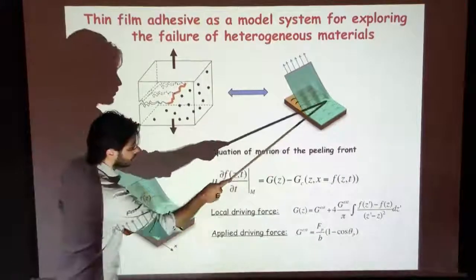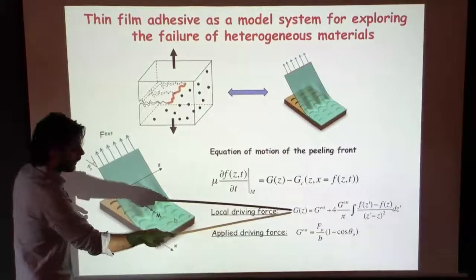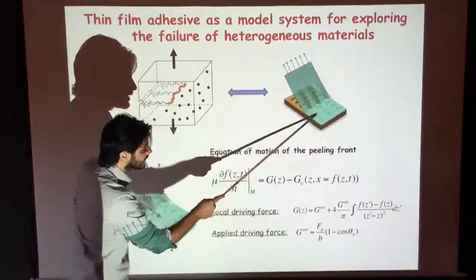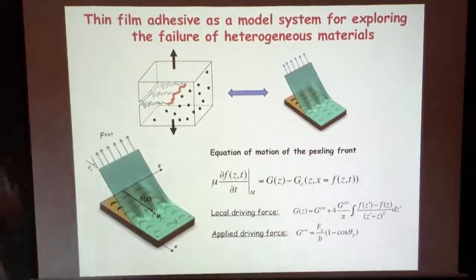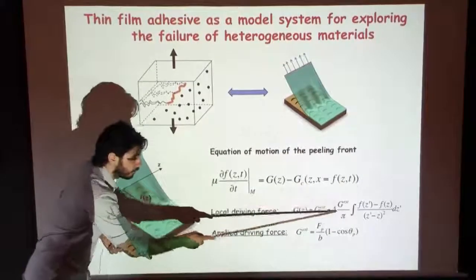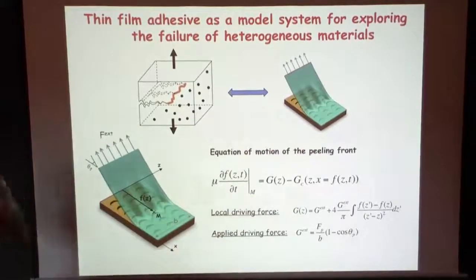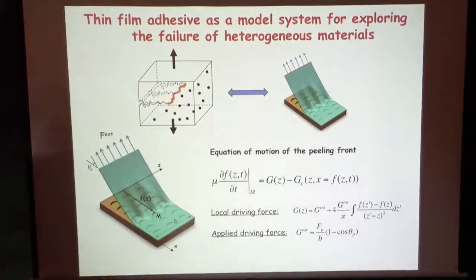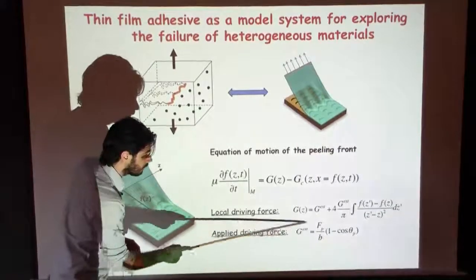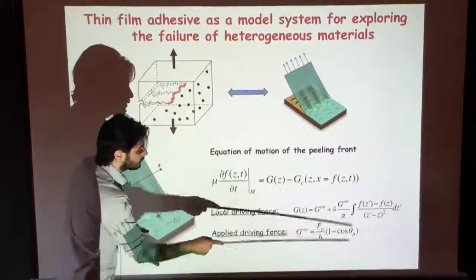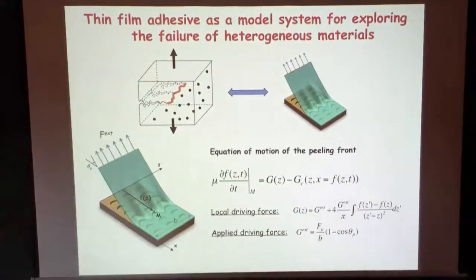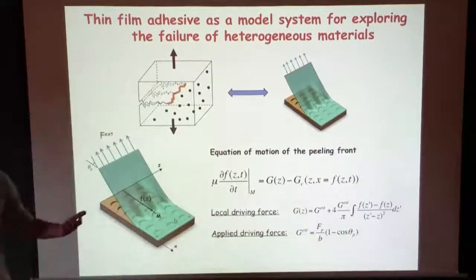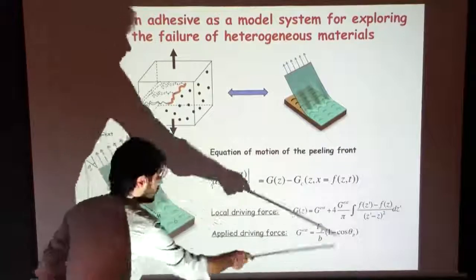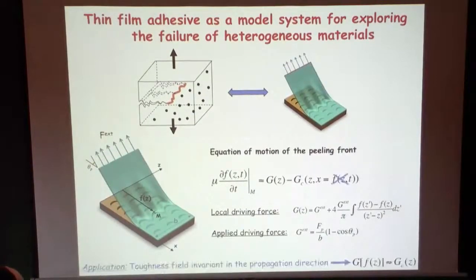And you can also consider a perturbation of your front, and the pseudo-elasticity of your line is of the same type as in the crack front problem. The only difference is a factor of 4. Here you have an elasticity of your line that is 4 times larger than the crack front elasticity, so you will have an amplitude of deformation 4 times smaller. But that's not a big price to pay. And then the applied driving force has a different expression as a function of the geometry of your system and loading. Instead of being proportional to the square of the applied force, it's not linear in the force. And there is a dependency on the peeling angle, but that's also not a big problem.